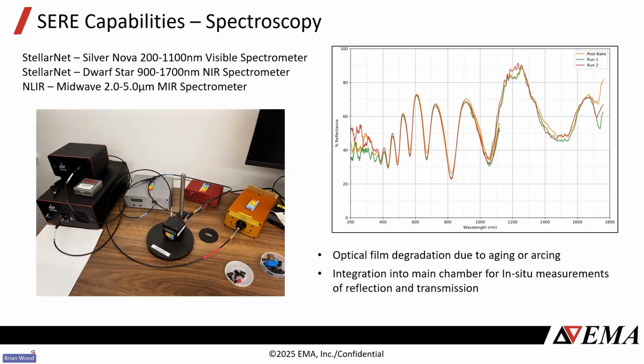I mentioned before, we do have some spectroscopy capabilities, and we've got a couple of StellarNet spectrometers that range from 200 to 1700 nanometers. We also have a mid-IR spectrometer. Depending on what you're trying to do, one use case is optical coatings, where people give us a window with a specialized optical coating that's going to be exposed to the space environment. We're able to irradiate the coating and the lens in our main chamber, and depending on the measurement you want, we can even integrate reflectance or transmission capability into the chamber.